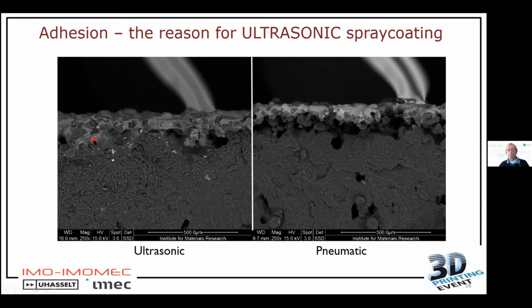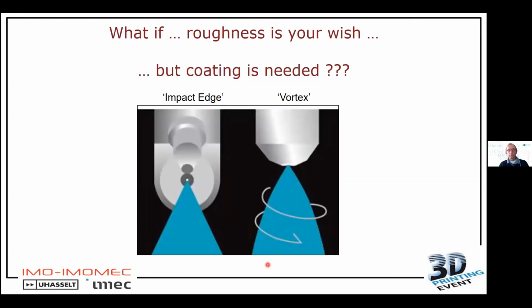The thickness does not increase, or the size does not increase, but also adhesion is improved. Here, the adhesion is between the porous surface of the 3D printed part, the PA12, and your added material. Here you really have a good mix of these materials, and the adhesion is improved. So this is, let's say, the reason why ultrasonic spray coating is such an interesting technology to do post-processing of additive manufactured pieces. Of course, this ultrasonic spray coating system can also be used for other applications.